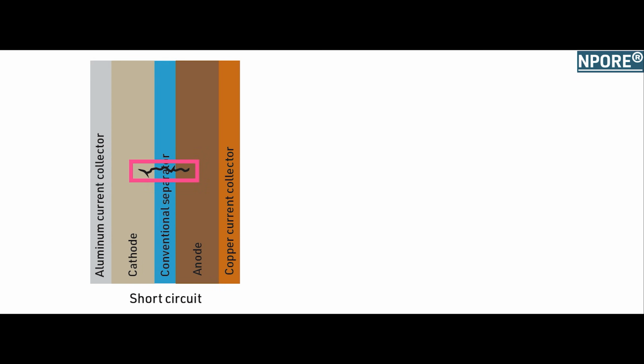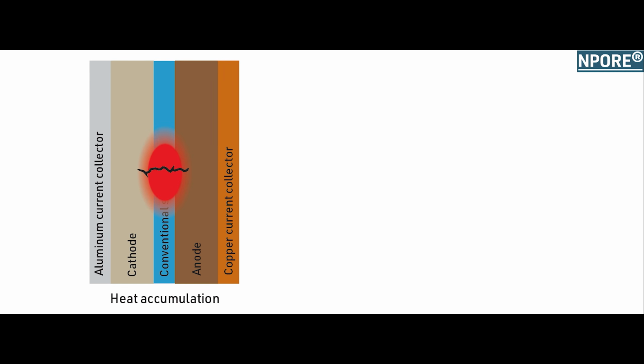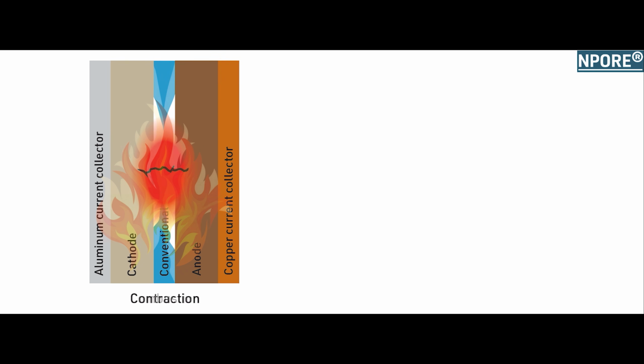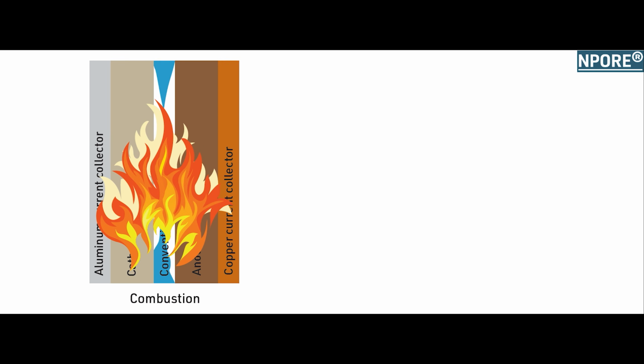Dendrites occur when lithium hasn't absorbed into the cathode or anode quickly enough and builds up on the electrodes. If the dendrites get tall enough, they can form a bridge between the cathode and anode, shorting it out. When that happens, energy flows across the bridge, releases heat, and melts the separator. That causes the separator to contract and more of the cathode and anode touch, which releases more heat, and eventually the entire battery cell goes into thermal runaway.